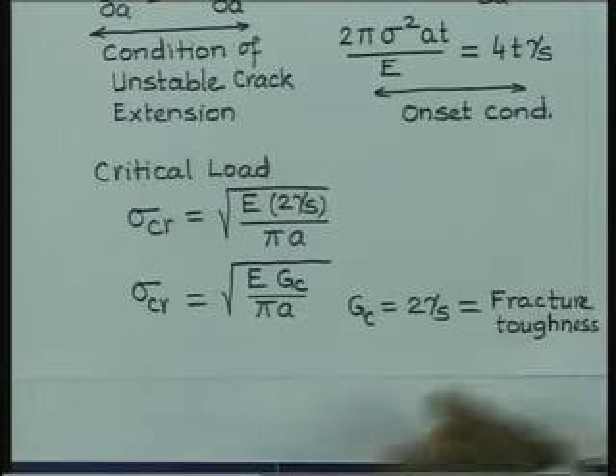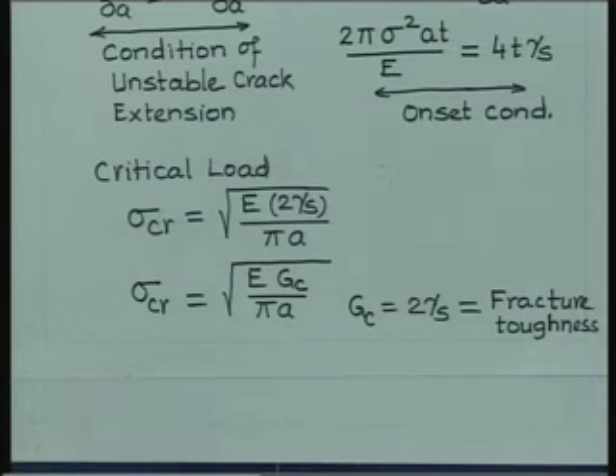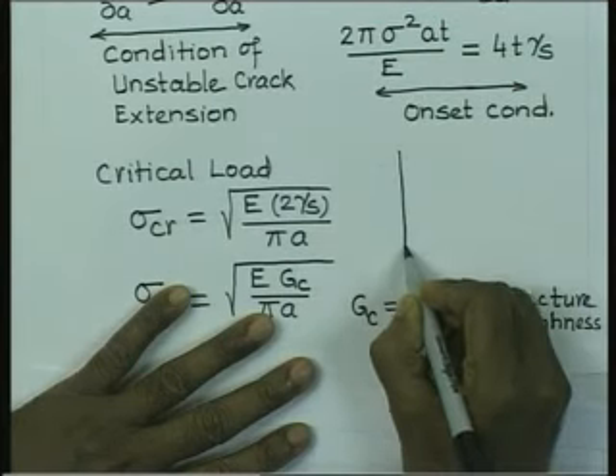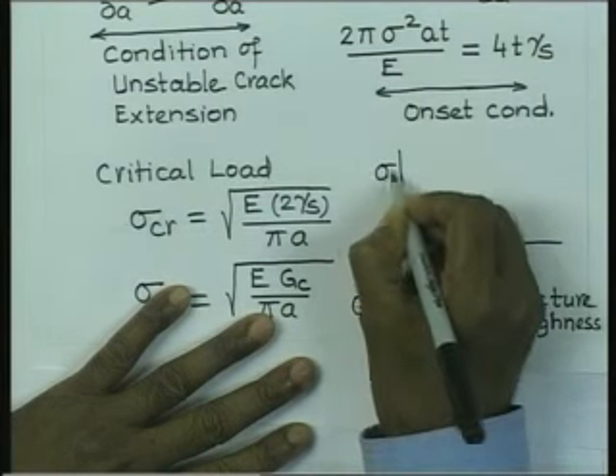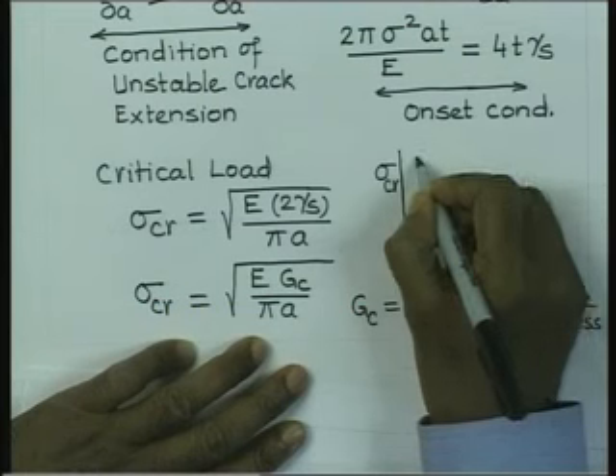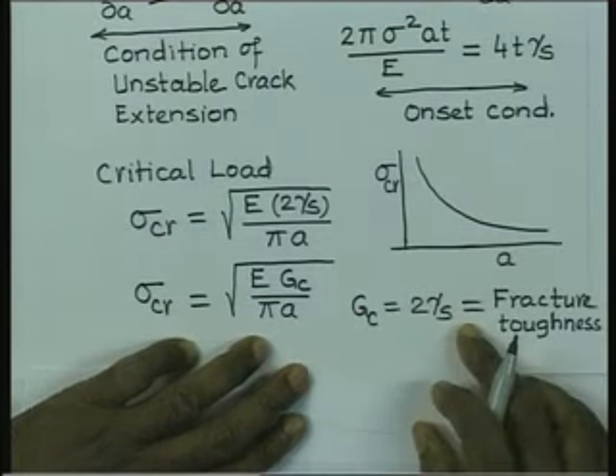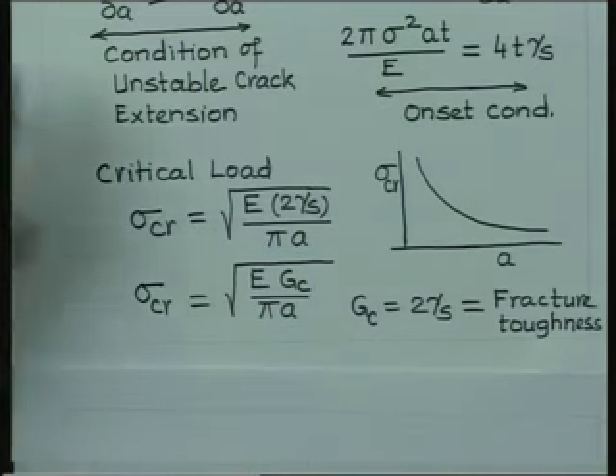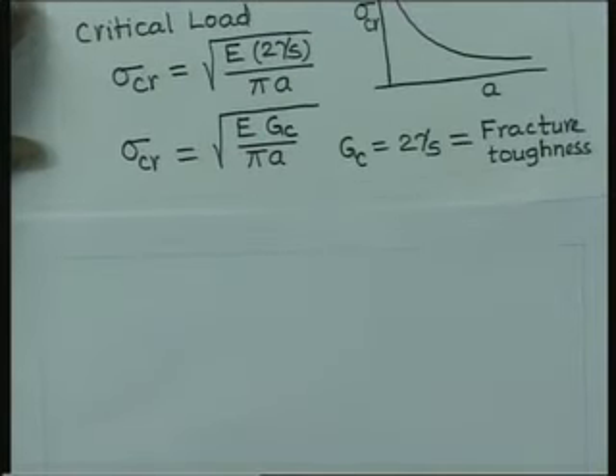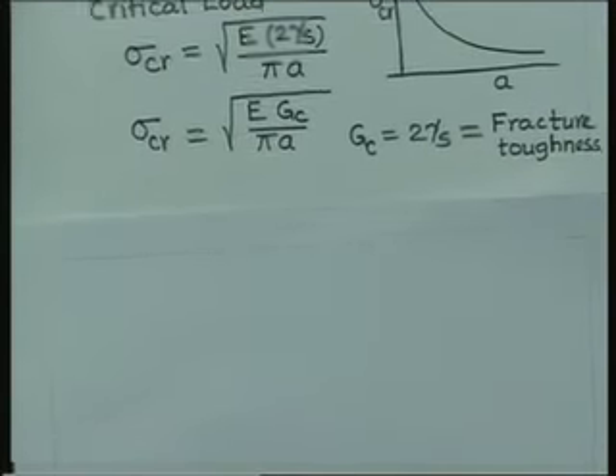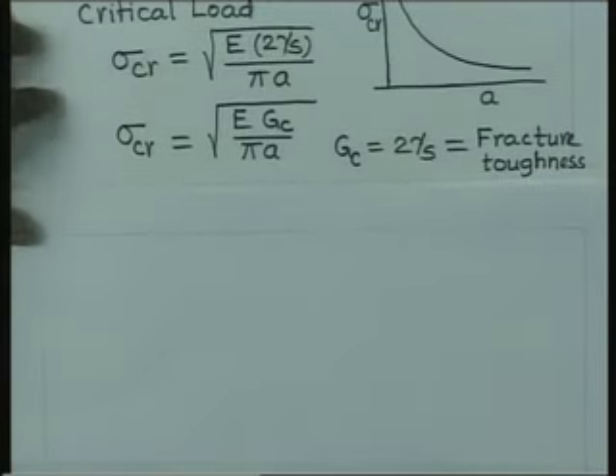In fact, Griffith did experiment with glass fibers and he showed that the variation of this critical load with the crack dimension varies as expected, it is going to vary like this. So, therefore, it was experimentally verified that this rule is correct. This particular relationship has a lot of practical meaning. It gives you for the first time the capability of calculating the load capacity of a component with defect.